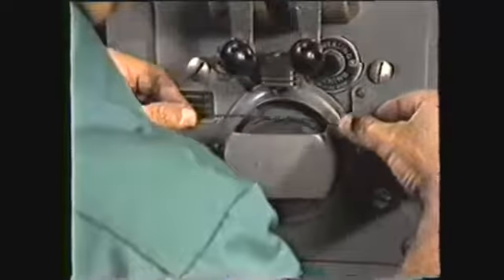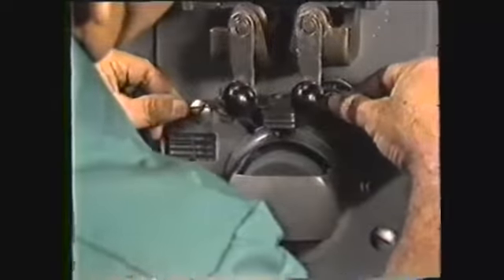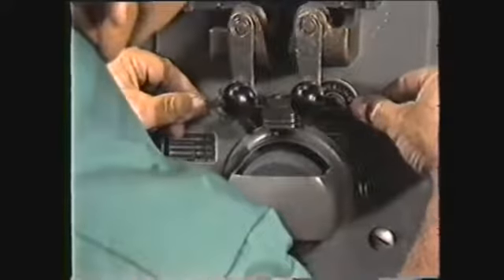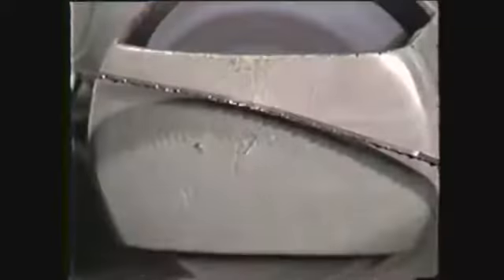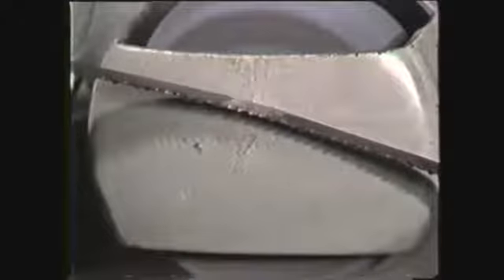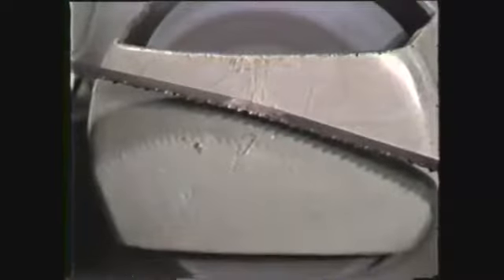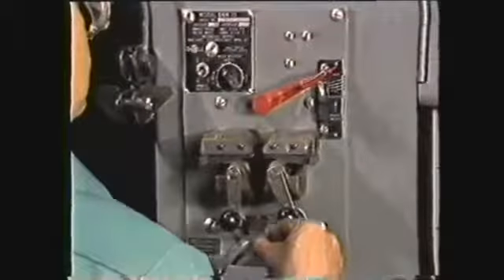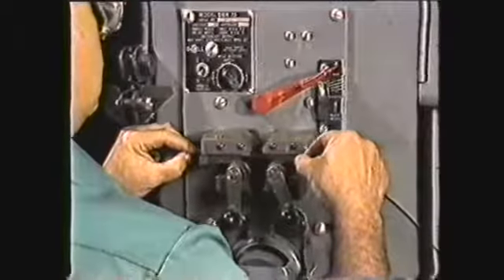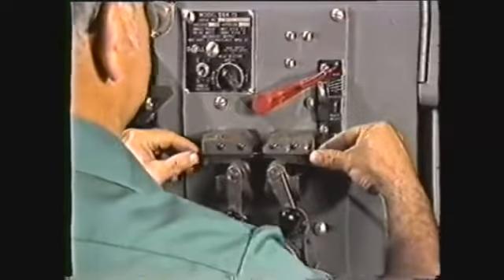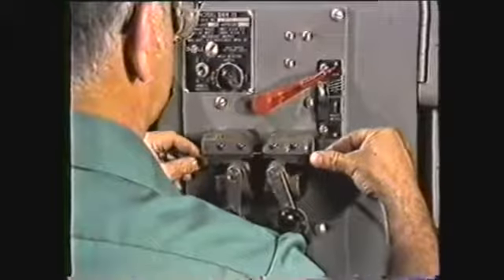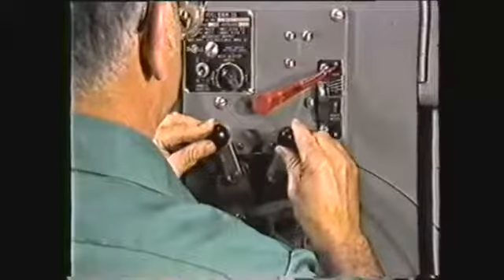Finally, check the blade thickness at the weld area with the weld grinding gauge. You should not remove any more metal than is necessary to reach the proper blade thickness. You may anneal the blade again after the grinding operation. This second annealing will eliminate any hardness which may be induced by grinding. The dull red color will show up very clearly on the ground surface.